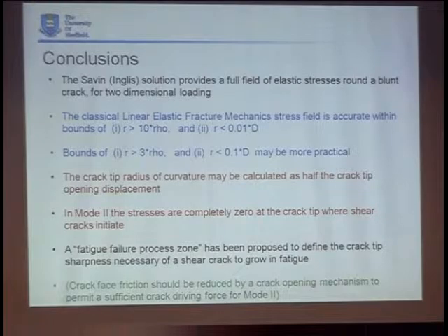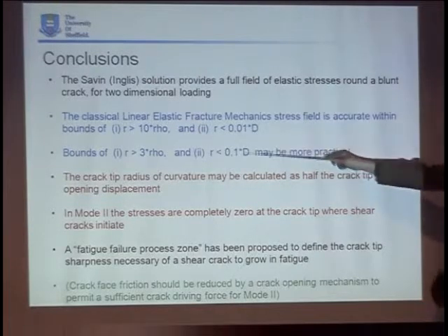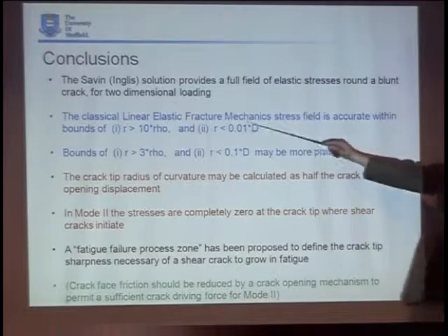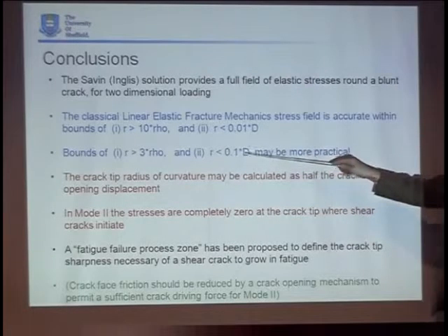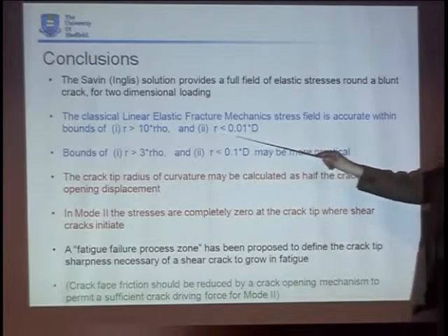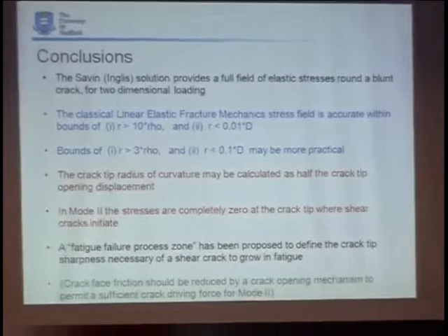Conclusions are there on limits of fracture mechanics, which are important. I've not mentioned the one at the top end. 0.1d comes up quite a lot. Perhaps to be more accurate, make it 0.01, depending on what errors you require, is also a lower limit. However, I could reduce all these conclusions into one, if you like, courtesy of apologies to William Shakespeare. We're looking at a mode 2 crack. We need to examine the crack tip stress field. Is the crack too blunt or not too blunt?